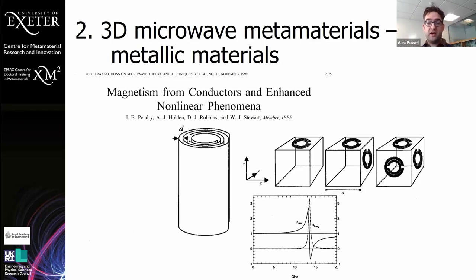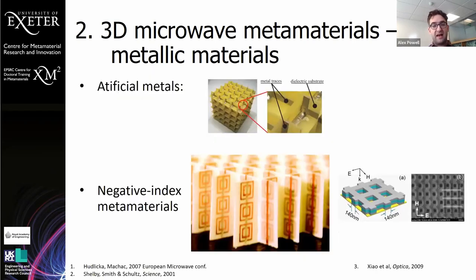And then we can do a converse thing to get negative permeability by creating current loops that give you magnetic behaviors. Traditionally people do this using split rings, and you can imagine making a 3D metamaterial with split rings that have negative permeability. Trying to make these has been difficult, and there's actually not been huge amounts of work on this, especially in the microwave.